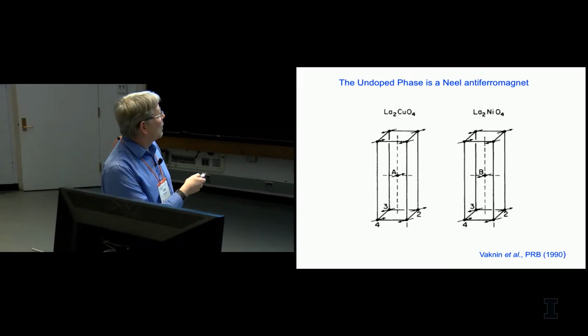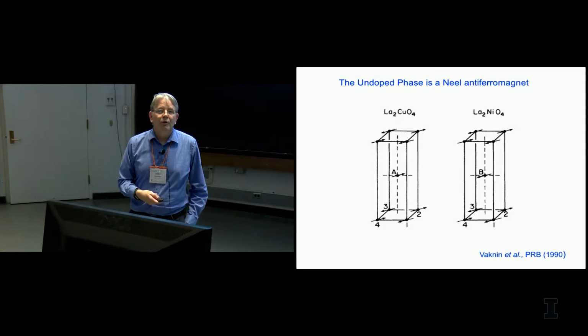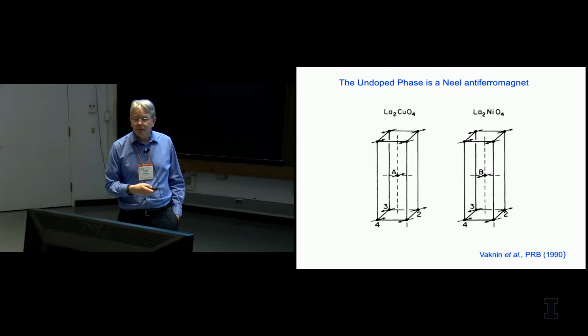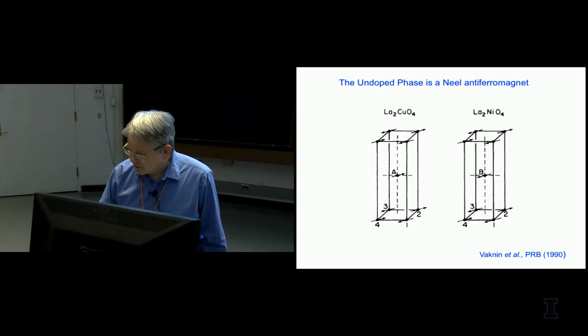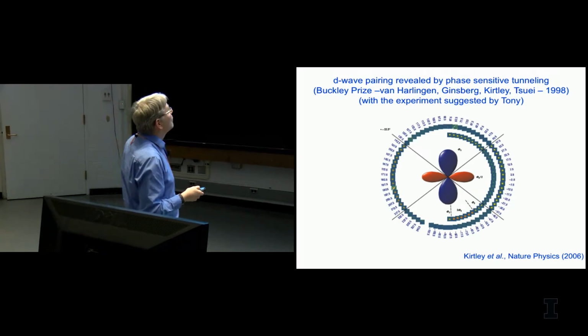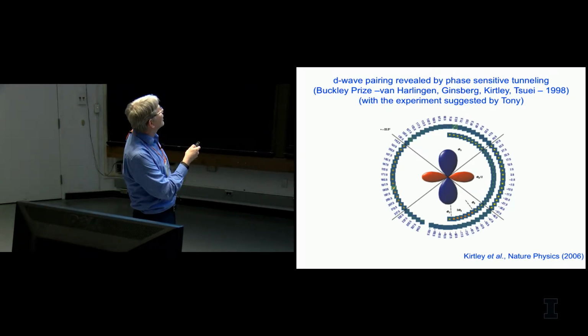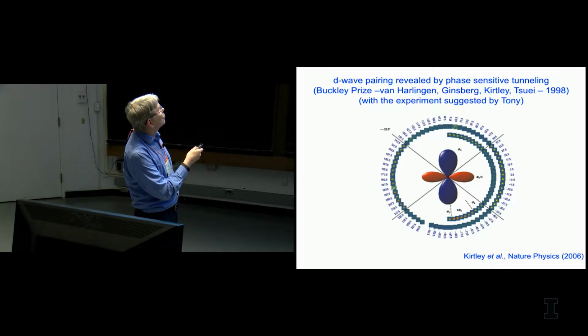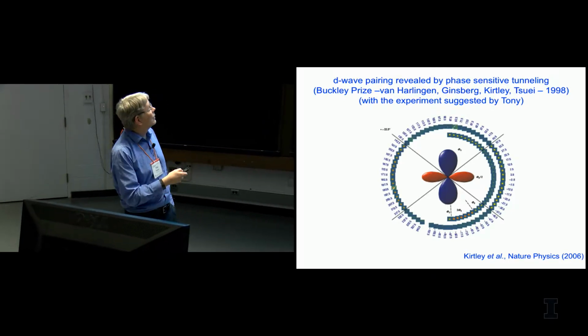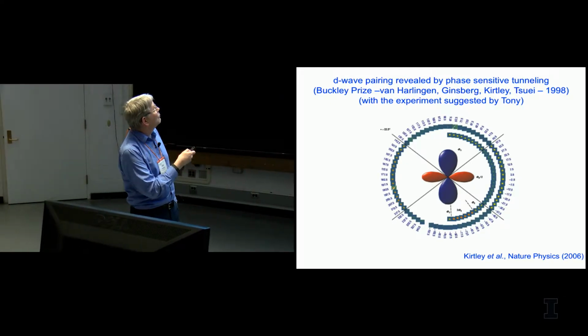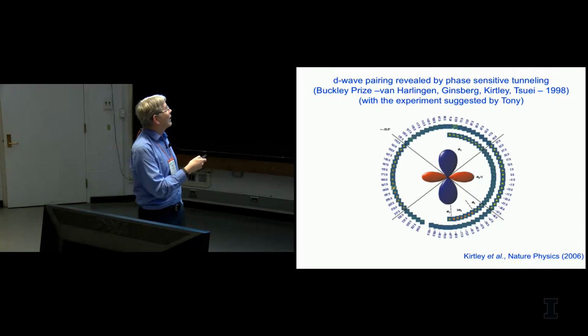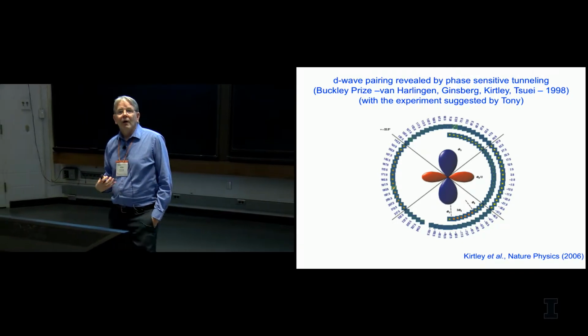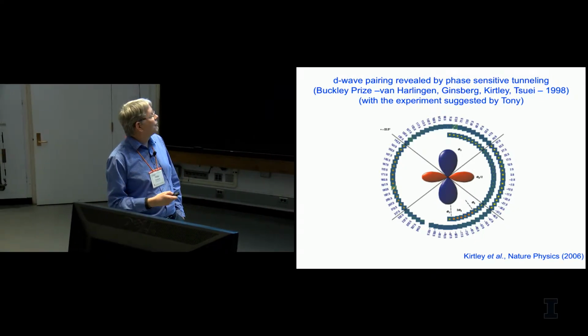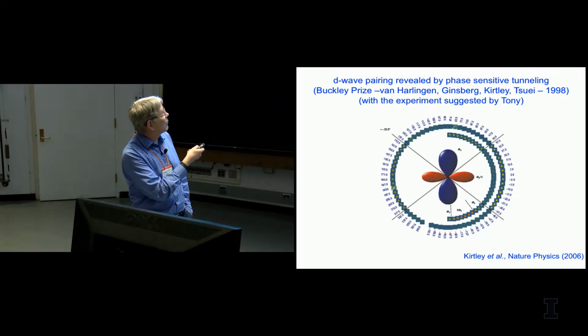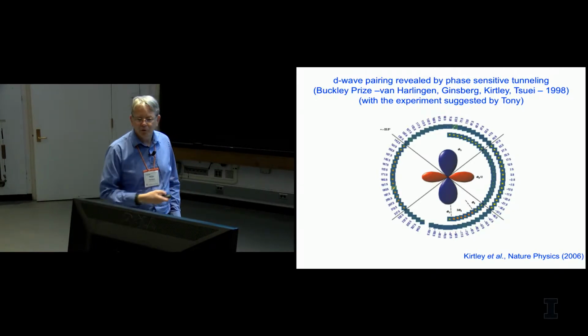On the other hand, magnetism disappears very quickly upon doping. So after a few percent hole doping, the magnetism disappears, and then you have this marvelous superconducting phase. And as was alluded to this morning, there was a lot of debate about what the superconducting phase was, and then Tony suggested this experiment that was carried out by Dale with samples made by Don Ginsberg, and some analysis experiments were done by John Kirtley and Chang Tsuei at IBM. And with this phase-sensitive tunneling, we know that we have a d-wave order parameter. It's actually quite spectacular because for almost all other known materials, in the unconventional case, we really don't have a definitive understanding of what the order parameter is, except for this example and, of course, helium-3.